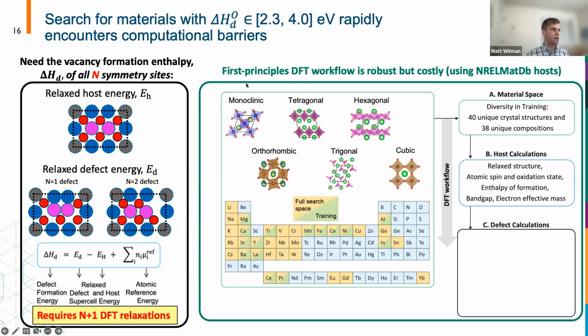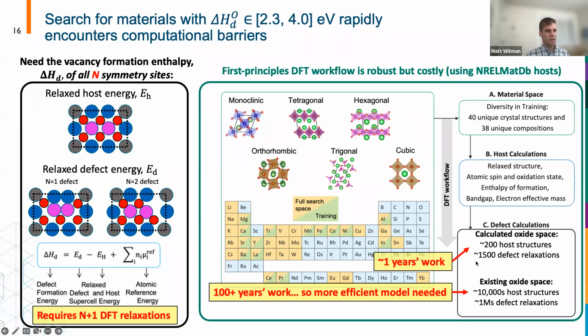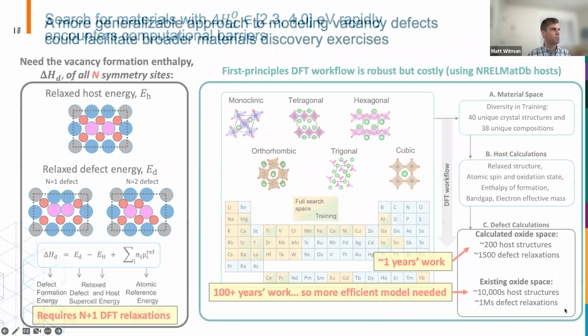So my collaborators at NREL have a nice first principles DFT workflow to do this, but it's still costly. So we built up a pretty diverse database of different crystal structures, different compositions, and done these detailed host and vacancy relaxations. And in about a year's time, we came up with about 200 host structures and about 1,500 relaxed defect enthalpy predictions. But in this kind of search space, if you go into Materials Project, you can find tens of thousands of host structures, containing millions of symmetrically unique defects. So you would never be able to just chug through this with brute force with DFT. So the goal is to drastically accelerate this process.